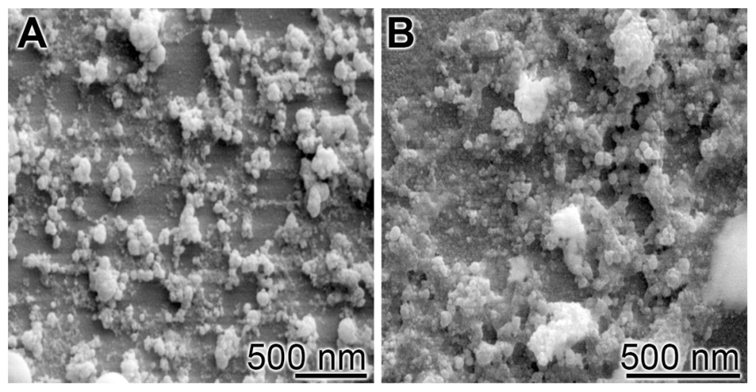Annealing is a crucial step in forming bulk parts due to the high thermal expansion of the material. Heat treatment of bioglass reduces the volatile alkali metal oxide content and precipitates apatite crystals in the glass matrix. However, the scaffolds that result from melt-quench techniques are much less porous compared to other manufacturing methods, which may lead to defects in tissue integration when implanted in vivo. The second method is sol-gel synthesis of bioglass, which is carried out at much lower temperatures than the traditional melting methods. It involves the creation of a solution composed of metal organic and metal salt precursors. A gel is then formed through hydrolysis and condensation reactions, and it undergoes thermal treatment for drying, oxide formation, and organic removal.